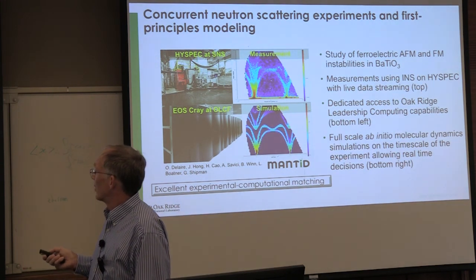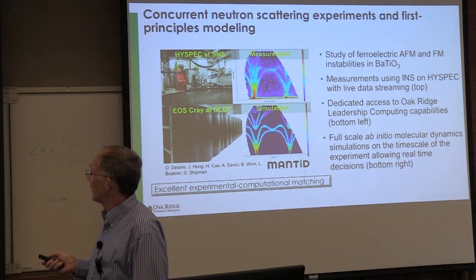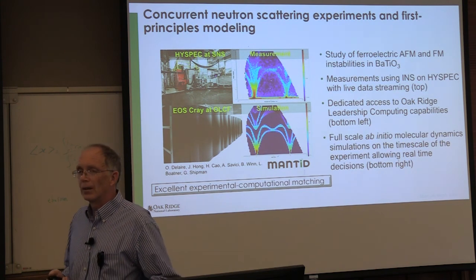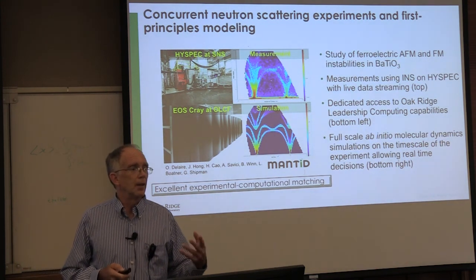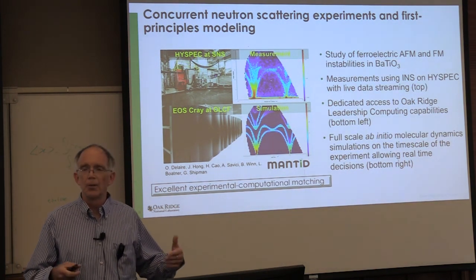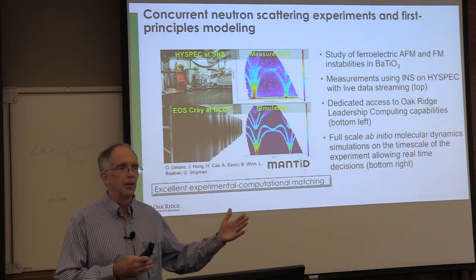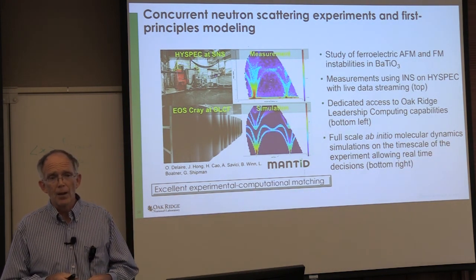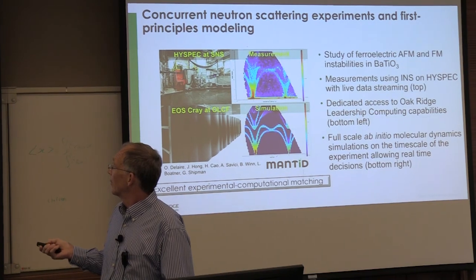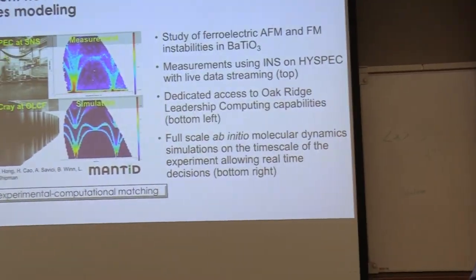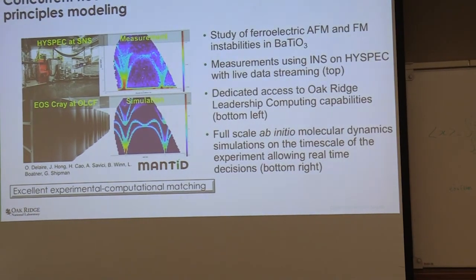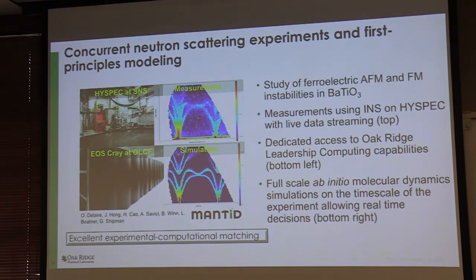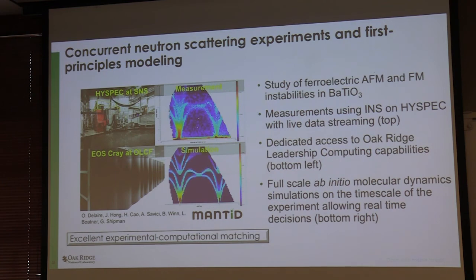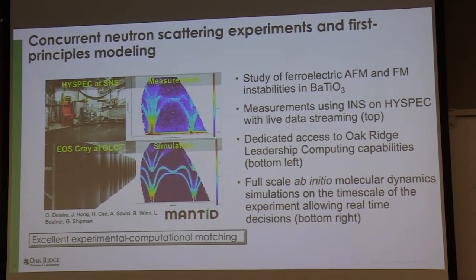So there's this inelastic neutron scattering technique that was done at the same time as we ran calculations to calculate what that should look like. As I mentioned before, we can always calculate things that can be compared to experiment directly. And we found some funky, interesting results in the calculations for a particular alignment that suggested a really huge degree of anharmonicity in these materials. This is barium titanate, a ferroelectric material that had never been observed before.